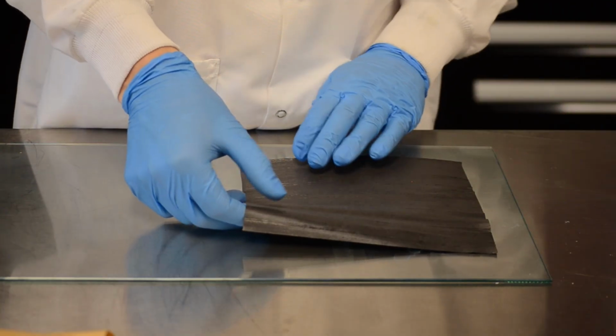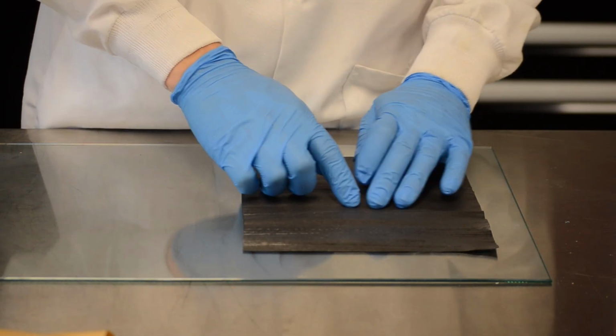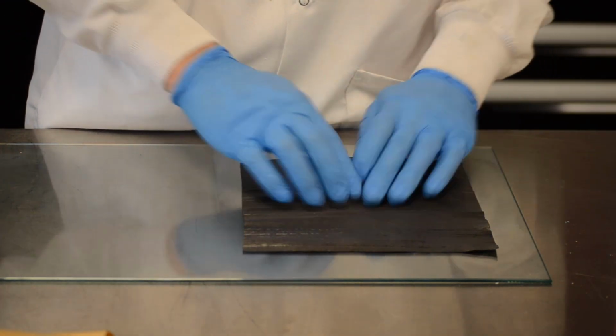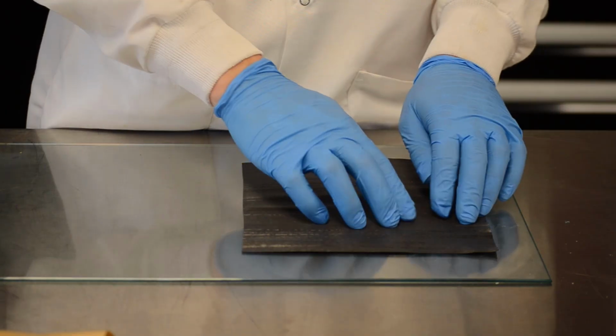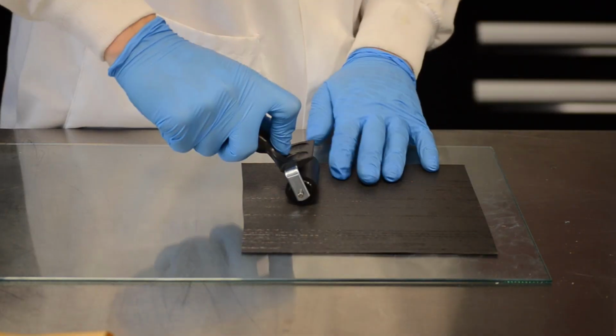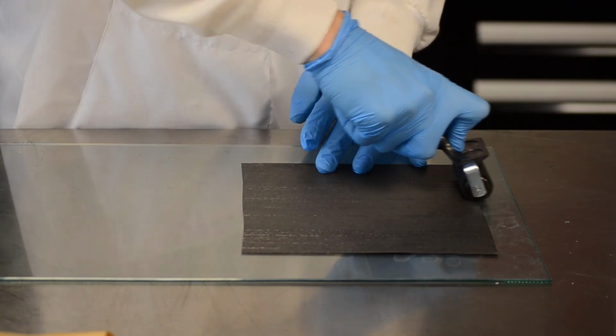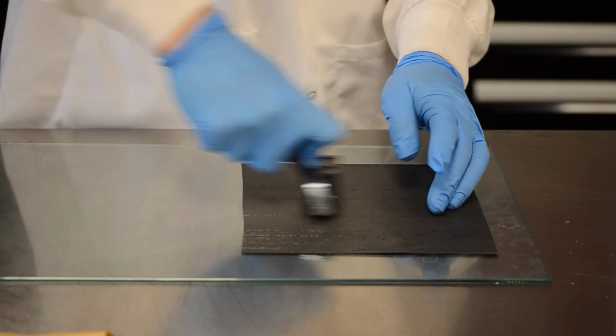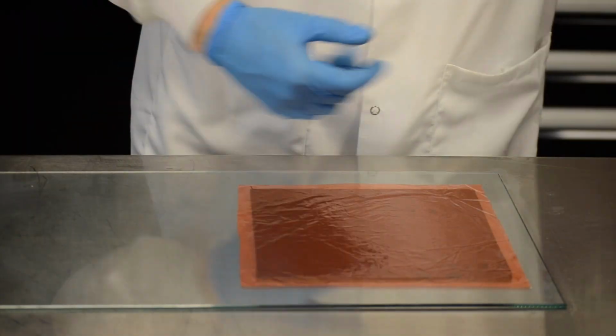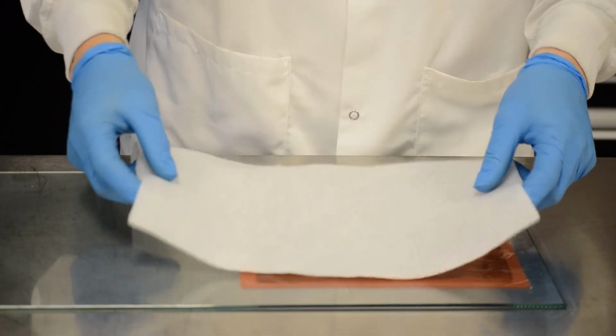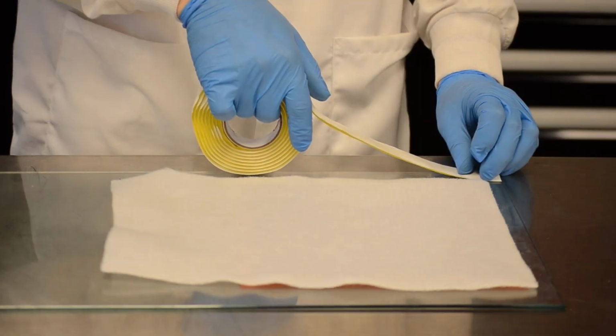We will then place the Prepreg in the desired spot and orientation on the tool. Alignment can be aided by laser projector systems that indicate the correct position on the tool. A roller can be used to consolidate the Prepreg layers. Rolling parallel to the fibers can reduce the chance of damaging the plies. After placing a number of layers, typically less than 5, debulking is performed.